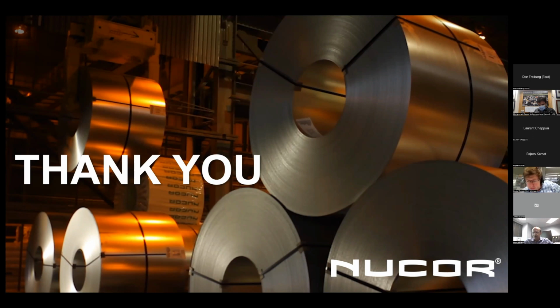Okay, thank you. And just one quick question that's come through the chat. Is there any EPA regulation for collecting or cleaning those oxidized elements? The oxidized elements all come out in the baghouse. I also didn't include zinc in there, because zinc ends up oxidized. It's not an element in the steel. It's actually the coatings that get oxidized, and that gets picked up by the baghouse.